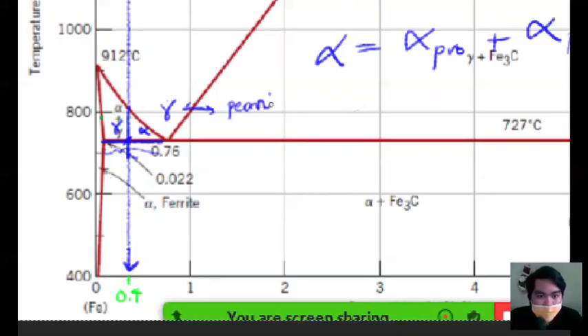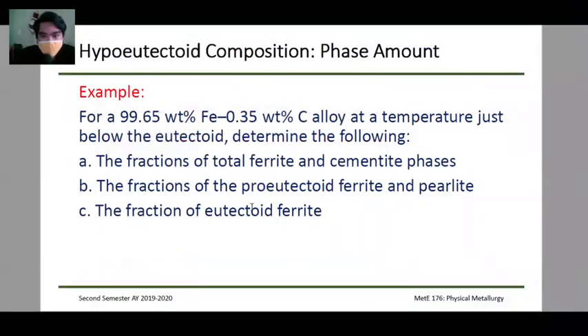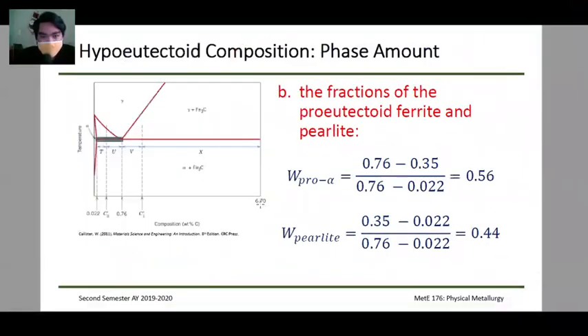Okay? And since we're doing slow equilibrium cooling, we are assuming that the microstructure we produce is pearlitic. So the remaining gamma, technically it should be gamma and alpha. But since we're doing this just below, all of the gamma remaining, if we do the calculations, it's 0.56 for the pro-alpha, and the 0.44 that remains, which is the gamma phase, has completely transformed into pearlite. So that's a pearlitic phase. That's why it is 0.44.